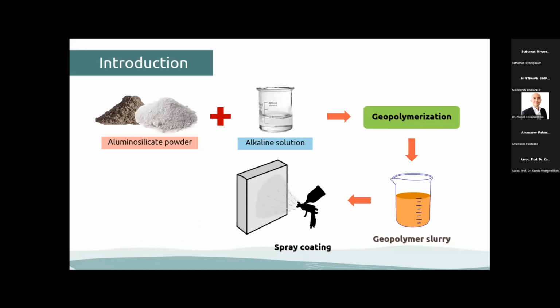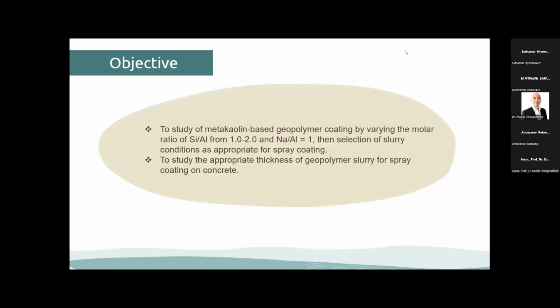Geopolymer is a cross-linked aluminosilicate structure synthesized by a chemical reaction, geopolymerization, of aluminosilicate powder with an alkali solution. The geopolymer slurry is then used for spray coating in this research. The objective is to study metakaolin-based geopolymer coating by varying the molar ratio of silicon per aluminum from 1.0 to 2.0, with sodium per aluminum equal to 1. Then select the slurry condition appropriate for spray coating and study the appropriate thickness of the geopolymer slurry for spray coating on concrete.